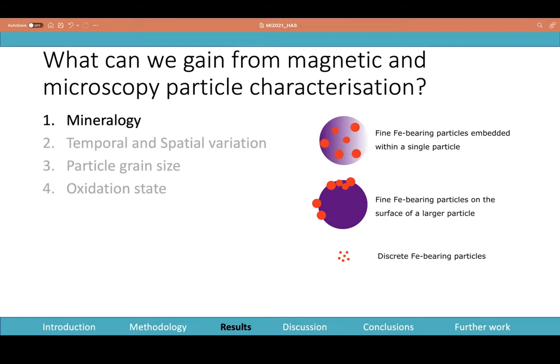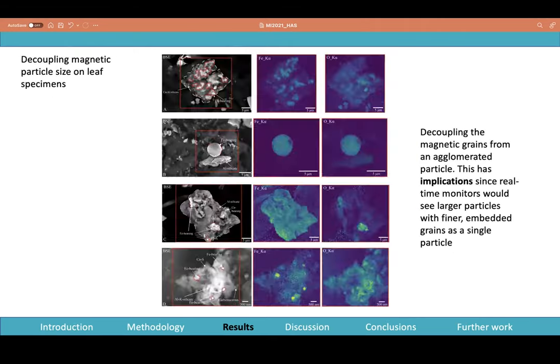So for the results, the aim was to see what we can get from a combination of these magnetic and microscopy measurements. As you can see in a very simple schematic, the Fe bearing particles in particular, the ones which we were interested in, were either present as discrete particles, or they were embedded on the surface of other larger particles, or embedded within carbonaceous particles or mineral dust particles.